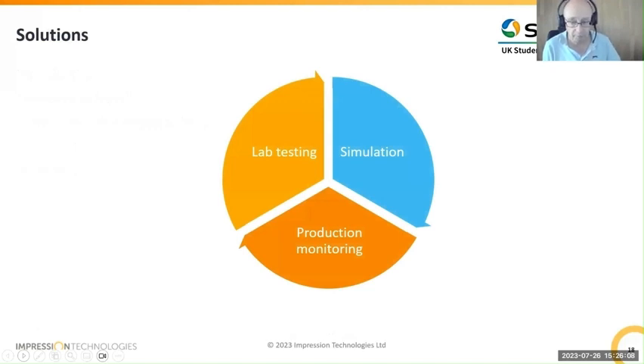Okay, so the way we go about screening lubricants is we begin with a series of lab tests where we can evaluate the lubricant performance and also its cleaning performance. And once we've done those tests, we can take measurements and pass information such as coefficient of friction back to our simulation team, who can then incorporate it into their equations for the simulations. One of the things we've always said to them is that you're going to have different numbers and different results to put into different parts of the design. One coefficient of friction number is not going to make your simulation work, and that's true of other forming simulations as well.